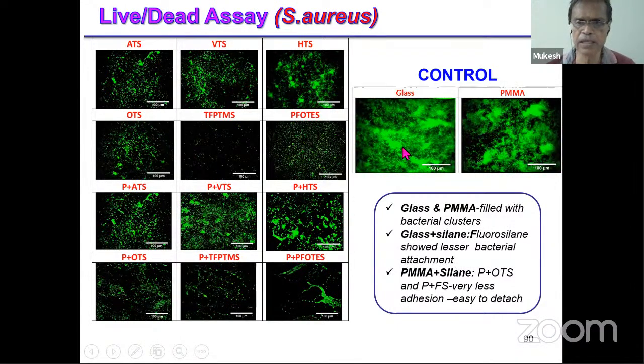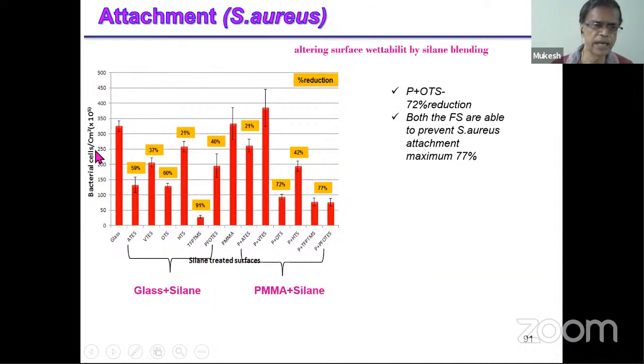Okay, this is the polymethyl methacrylate. This is the glass slides and different silane coating on the surface, and we see different extent of attachment of the bacteria. So attachment again numerically, we see that there is big difference in the colony forming units of the bacteria on the silanes.